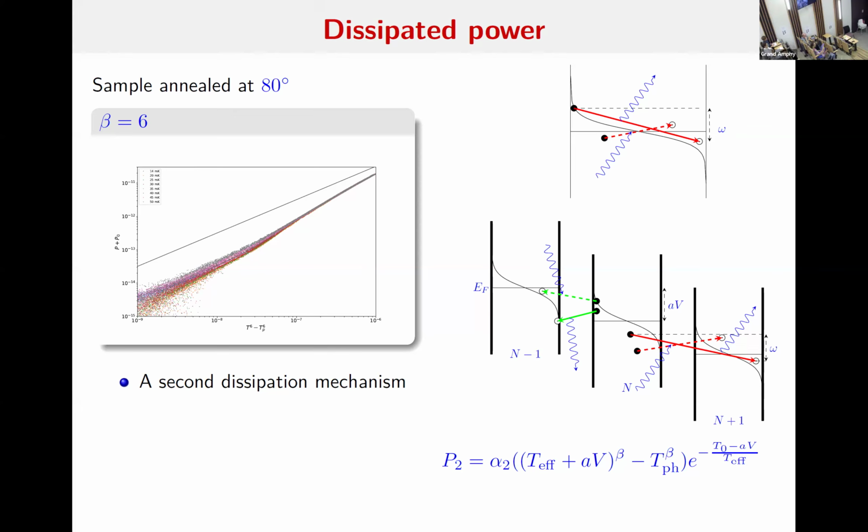So what we think is that in this case, there are other processes of relaxation. This is our explanation of the hot electron model: you have pseudo grains that are fairly large, and relaxation is by phonon interacting with electrons within a grain. And the reason why the formula of the power works, it's a formula for metal, is just because the grains are metallic grains, relatively large. So for this reason, this is working.